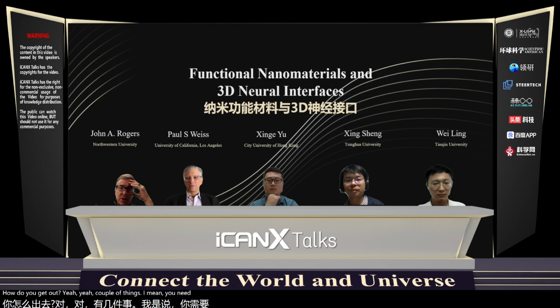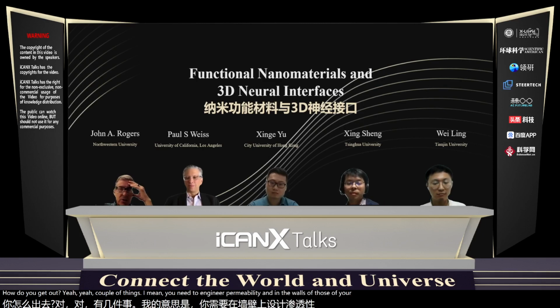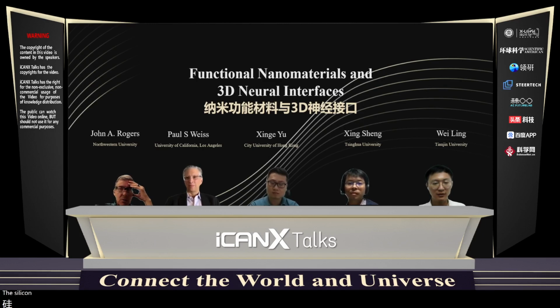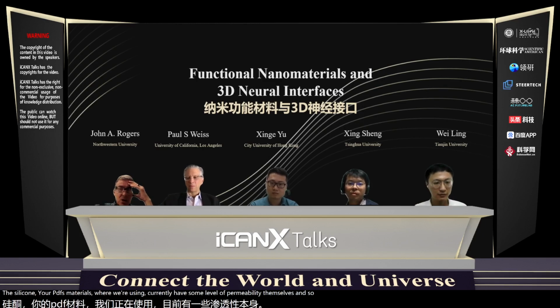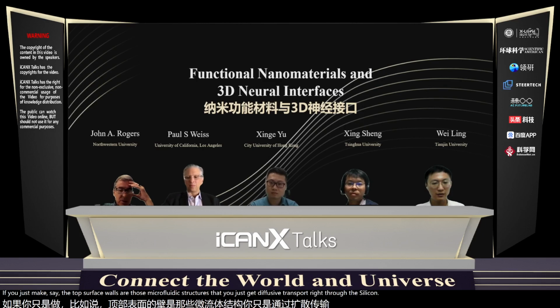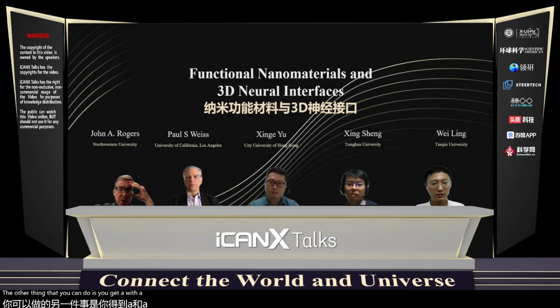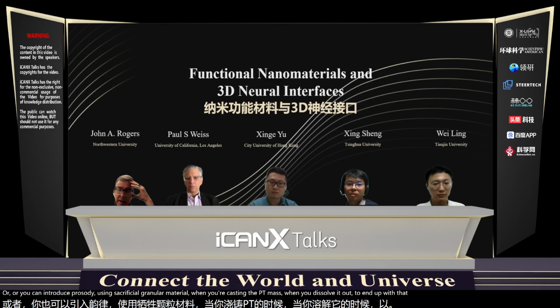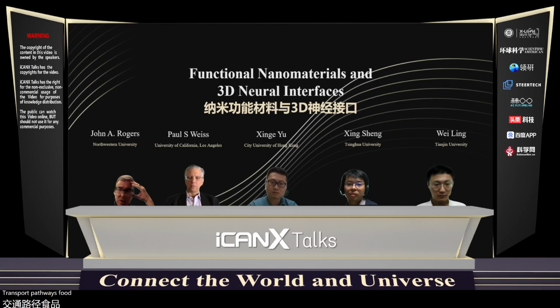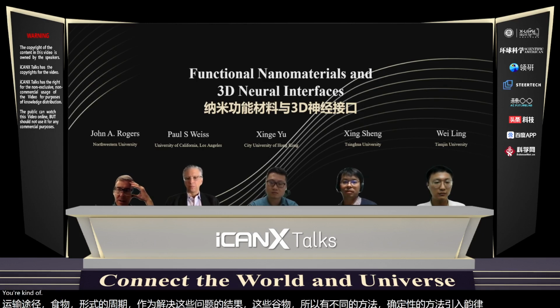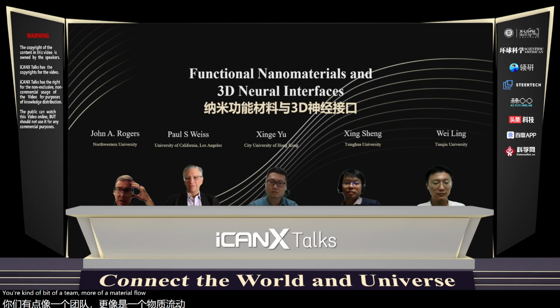There are a couple of things. You need to engineer permeability in the walls of those microfluidic systems, and there are a couple of ways to do that. The silicone PDMS materials we're using currently have some level of permeability themselves, so you can make, say, the top surface wall of those microfluidic structures thin enough that you get diffusive transport right through the silicone. The other thing you can do is lithographically define porosity, or introduce porosity using sacrificial granular material when you're casting the PDMS, and then dissolve it out. So you end up with transport pathways through the voids that form as a result of dissolution of those grains. There are different ways to do it: deterministically introducing porosity at more of a materials level, or just exploiting the intrinsic permeability of the material.